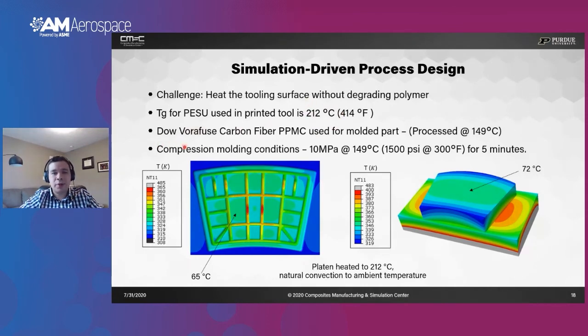The material we use for the compression molding is provided by Dow and is Vorafuse. It's a carbon fiber PPMC, and is processed at 150 Celsius or 300 Fahrenheit. The molding conditions we need to produce this part are 10 megapascals at the same processing temperature, so it's around 1500 PSI. This is a fast cure system. It only takes around 5 minutes to cure a part.